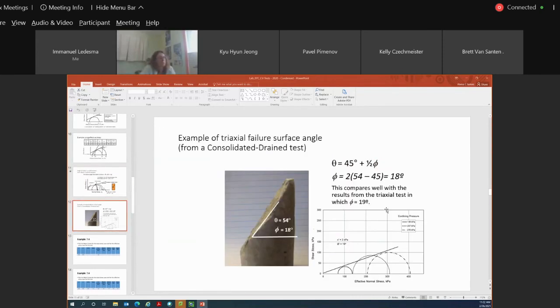And this is just an example where we calculated the friction angle from a CD test, and from that friction angle, using this formula, we were able to verify the angle of our failure plane, and we were able to measure the angle of our failure plane from our specimen, and they corresponded quite well. Okay.